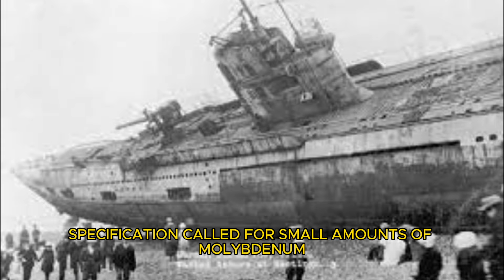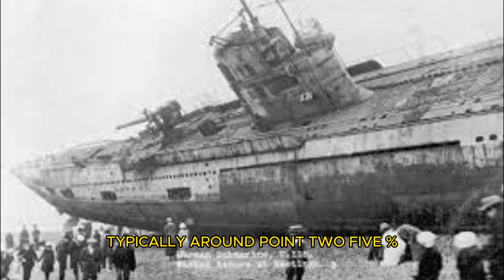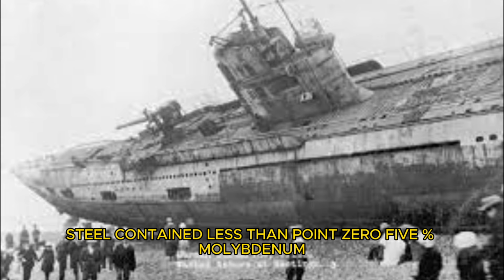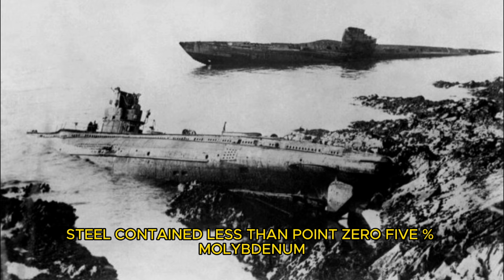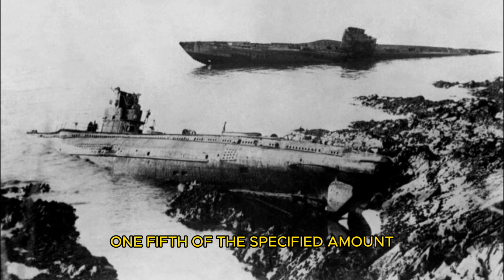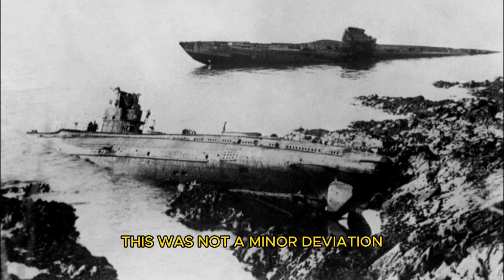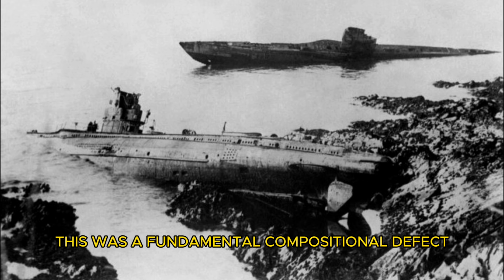ST52 specification called for small amounts of molybdenum, typically around 0.25%. Molybdenum is a critical alloying element in structural steel. It increases strength, improves toughness, prevents brittle fracture. The U-boat steel contained less than 0.05% molybdenum, 1/5 of the specified amount. This was not a minor deviation. This was a fundamental compositional defect.